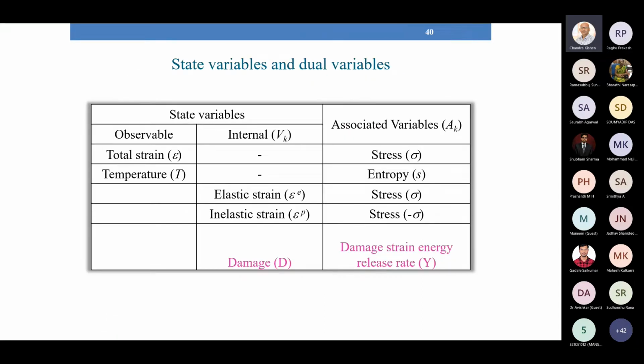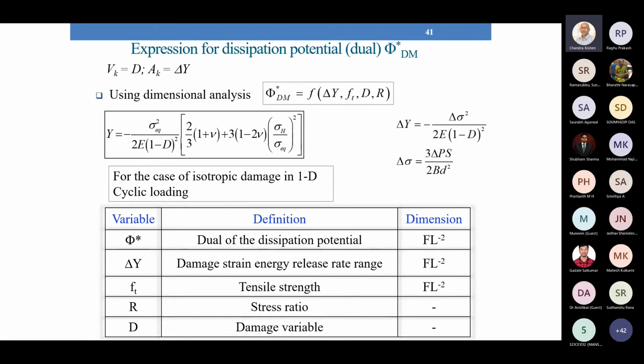So again, instead of taking the crack area as the state variable as earlier, we take a damage parameter, and then we have an associated variable, which is the damage strain energy release rate. Again, through dimensional analysis, we could obtain the dissipation potential from damage mechanics. So this is a potential from damage mechanics, DM.